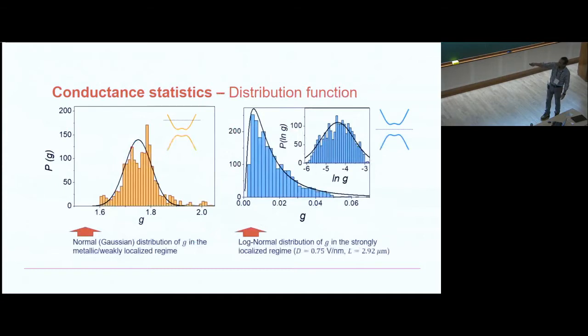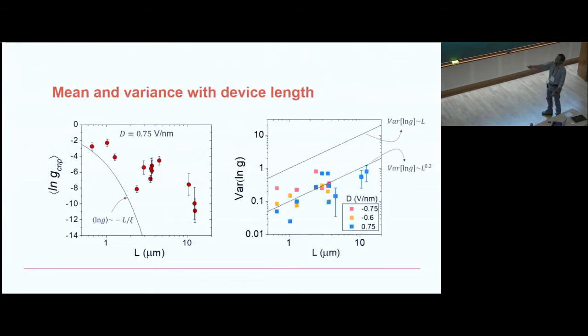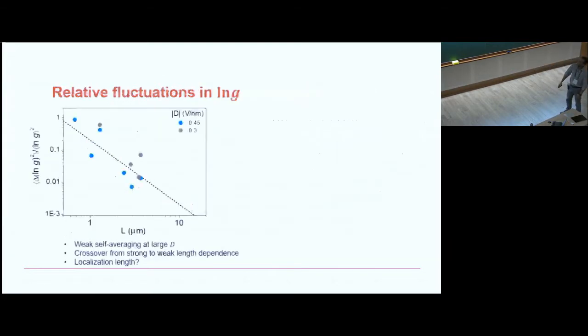What's interesting here is that if you are metallic, that is, the Fermi energy is in the conduction band, the probability density of the conductance fluctuations is beautifully Gaussian. But when you're in the localized regime, that is, the Fermi energy is inside the gap, then you have a log-normal distribution of conductance, very well known in the case of localized systems. And from there, we calculate the width and mean of the distribution. And this gives us some very interesting results. This is the variance of log G, which increases slightly, and this is the mean of log G, which decreases as you increase the length. This is the most important part of the result. I'm out of time, so I'll quickly finish it.